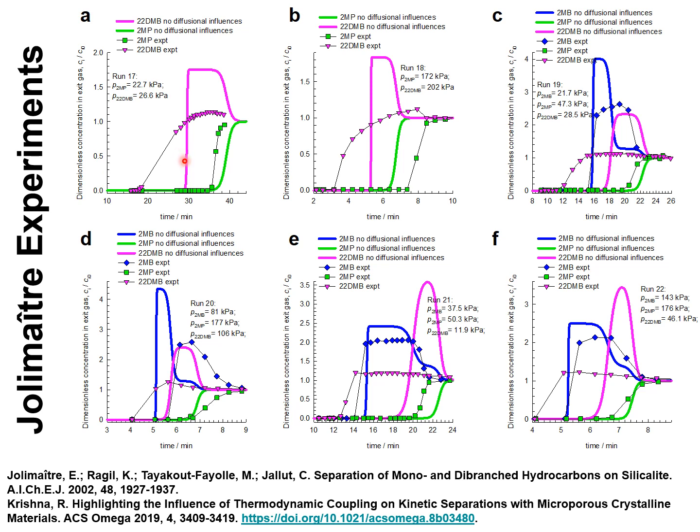Indeed, diffusional influences are helpful in the separations because there is a wider gap between the breakthrough times from experiments than those anticipated by a model that ignores diffusional influences. Put another way, adsorption and diffusion act synergistically in runs 17 and 18.